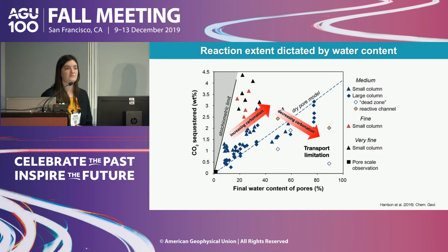By excavating our columns at the end of the experiment, we could correlate the amount of reaction with the water saturation with depth. That's what's shown here, where we have the amount of CO2 sequestered on the y-axis, so essentially the amount of carbonate minerals formed, versus water saturation on the x, where we typically observed a reduced amount of reaction at low water saturation that starts to increase as water saturation increases and declines again at very high water saturation. Now, the reason for this decline at high water saturation is essentially a transport limitation, not a reaction limitation. You get increased development of preferential flow paths at high water saturation, so a lot of the porous media is just bypassed by that CO2.